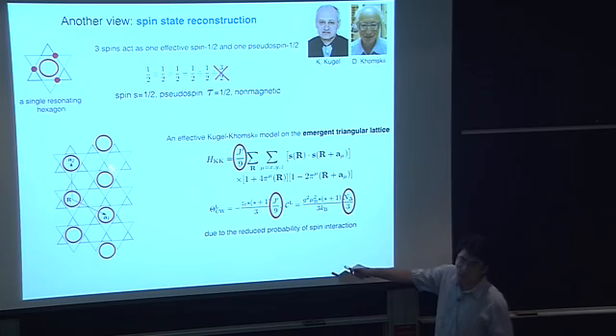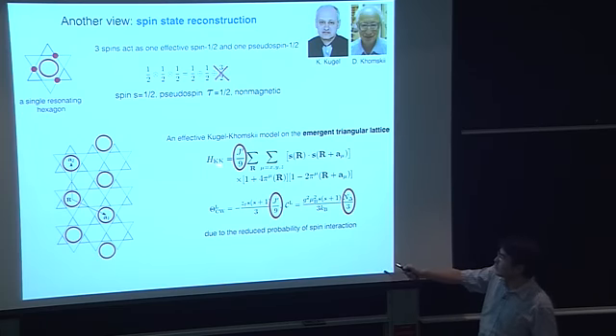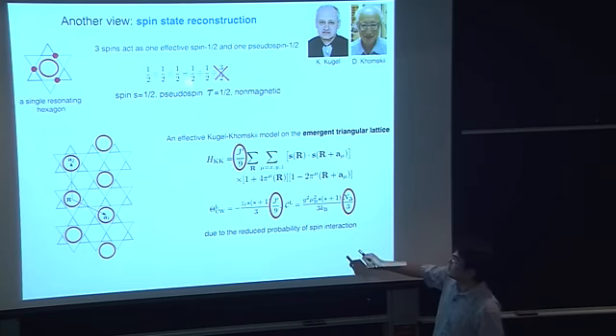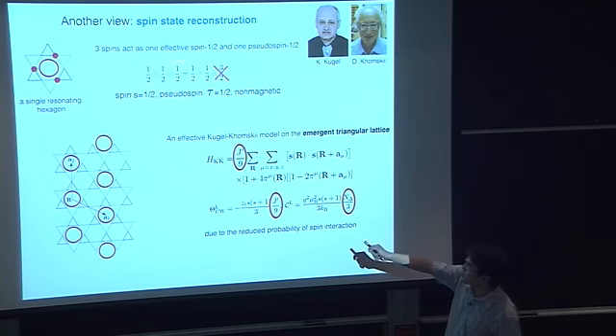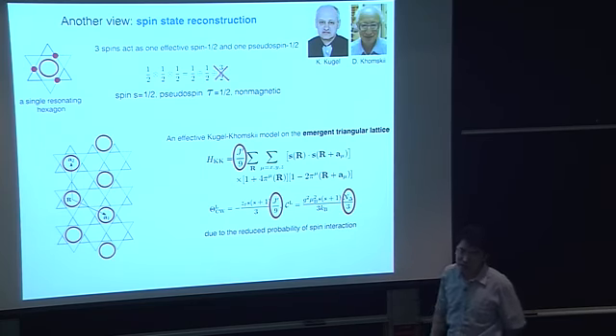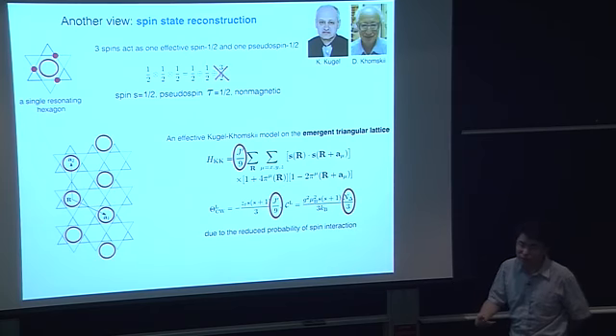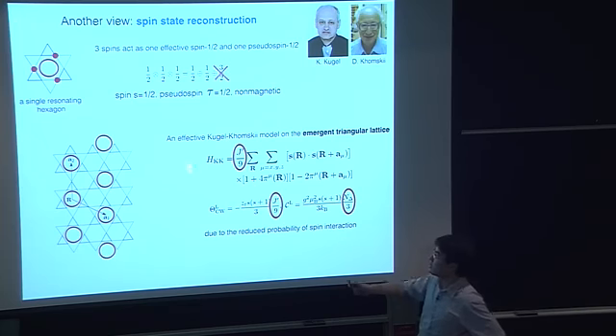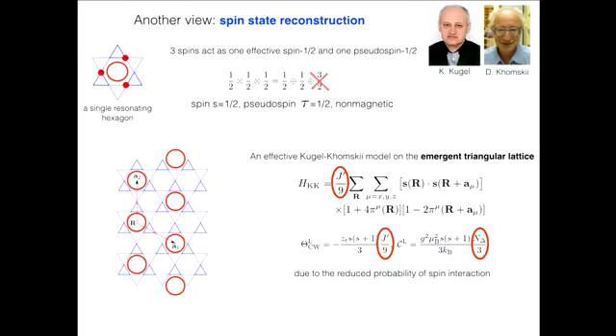So the effective model to describe the interaction is a Kugel-Khomskii model, because we have a pseudo spin 1/2 and a spin 1/2. One can actually derive the model, and because 3 spin 1/2 electrons effectively behave like 1 spin 1/2 local moment, that will naturally explain why we have the 1/3 spin susceptibility anomaly at low temperature. So that's one more physical explanation in terms of spin state reconstruction.